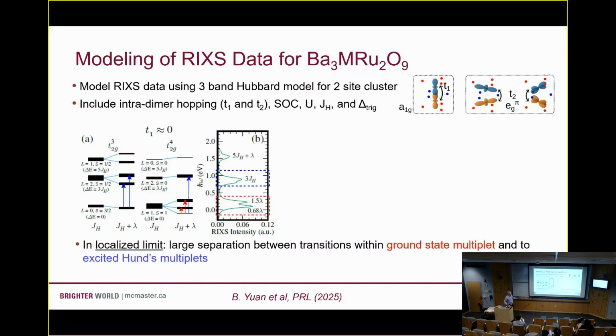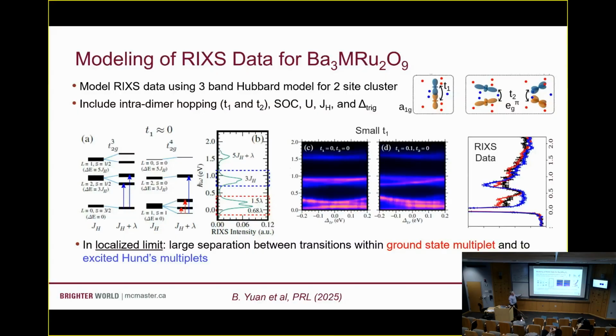Okay? We get large separation between the transitions within this ground state multiplet and the excited Hund's multiplet. These ones, the energies are set by lambda. These ones, the energy is set by the Hund's coupling. Okay. We can introduce small t1. So turn on the hopping, but keep it small. And what you can see is that, again, we can play around with the size of this trigonal crystal field splitting. Okay, so that was the key to describing the LMRO in the last story. But here you can see that the RIXS spectrum varies smoothly across here for either positive or negative crystal field splitting, so either stretching or compressing our octahedra. And in no case here do we find a way to suppress these low energy states here.